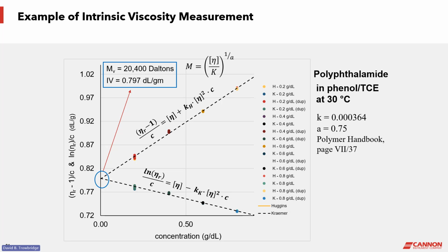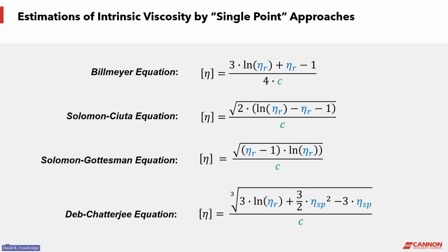But on the flip side, some methods try to shorten the analysis by using what's called single point approach. Some researchers take these early working equations and made some manipulations, some assumptions, some approximations, and came up with expressions for intrinsic viscosity that are based on just one measurement of relative viscosity at one particular concentration. So that's why these are called single point approaches, because they estimate intrinsic viscosity based on just one data point, not involving an extrapolation like the more rigorous approach.